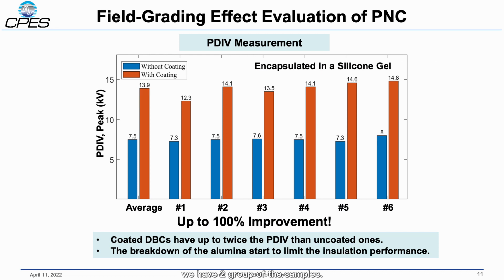As I mentioned, we have two groups of samples. One group is with the coating. We first coat the PNC at the edges of the copper, and then we encapsulate them in the silicone gel. Samples without coating were also prepared.